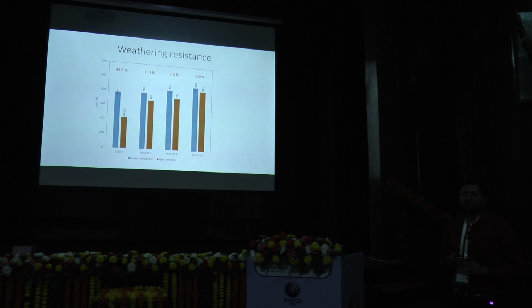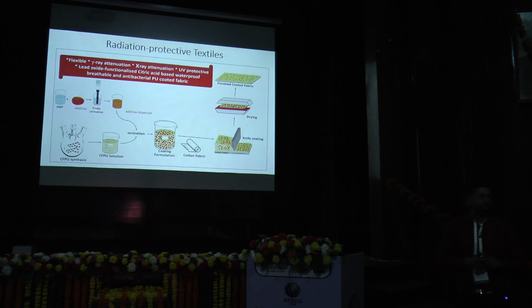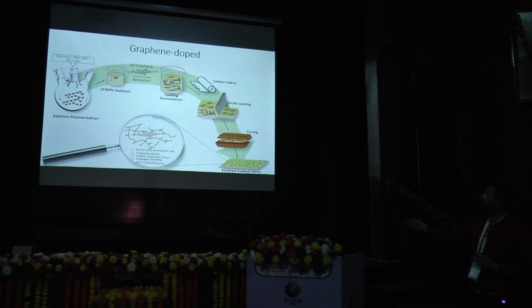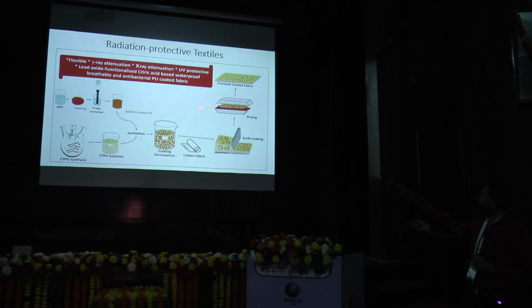Then we have tested weathering resistance because if the fabric is used for outdoor application, weathering is very important. UV light, rain, all kinds of accelerated weathering is required. So we tested it, we found that the uncoated cotton has strength loss and the color is changed, but in case of coated, strength loss is not that significant and color was also not changed. So that gives us good confidence in this product. Then we move to radiation protection. Like I said, we want protection from high energy radiations like X-rays, gamma rays and all. So in this case, we have added the filler in this polyurethane, and then it is formulated and again coated on fabric.